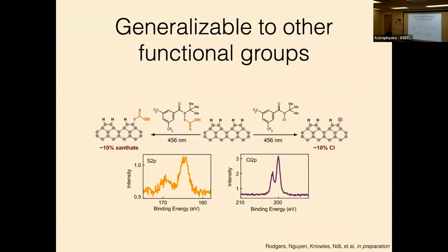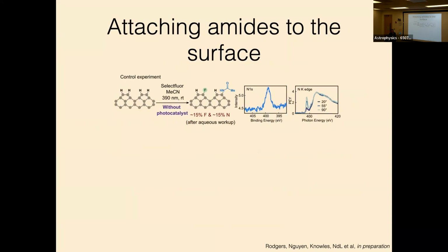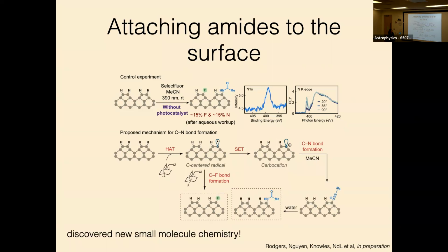All right, once we have that first hit, it turns out that this chemistry is very generalizable to many other functional groups. We can put sulfur-containing xanthates on the surface. We can put chlorine on the surface, and it's all very, very broad. The other thing that we discovered is a method for being able to attach amide groups to the surface, which are very helpful for functionalization. It was a little bit of an accident, and this is a mechanism that we were not expecting. But the kind of neat thing is that what we were able to do was come up with a proposed mechanism for putting this amide group on the surface. And then we could take that back to these diamondoid molecules and then verify that the chemistry worked using liquid NMR.